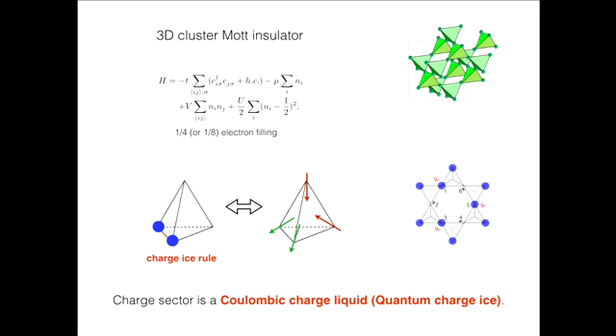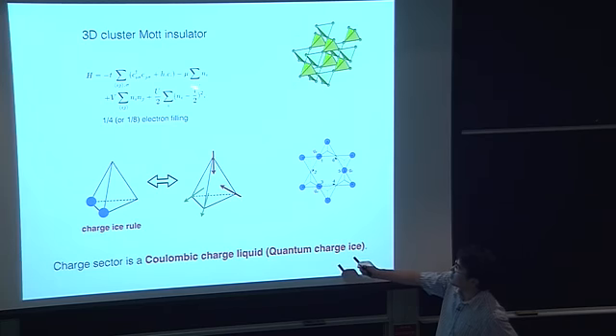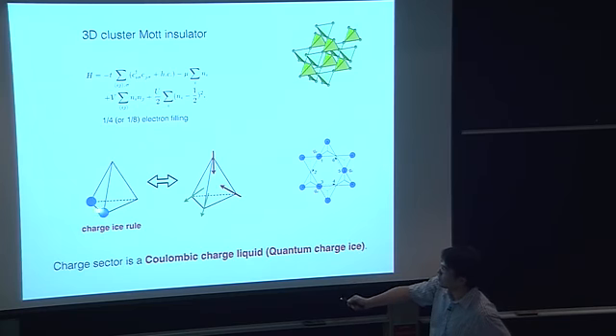So yeah, three-dimensional cluster Mott insulator as a manifestation of quantum charge ice. I consider this kind of extended Hubbard model, which is similar, but preserves the inversion symmetry of the pyrochlore lattice. This is the pyrochlore lattice. It's called shared tetrahedra. In a large U limit, which only allows single occupancy or zero occupancy, at 1/4 filling, if the inter-site repulsive interaction is very strong, the electron will be localized in the tetrahedron. There will be 2 electrons in each tetrahedron.